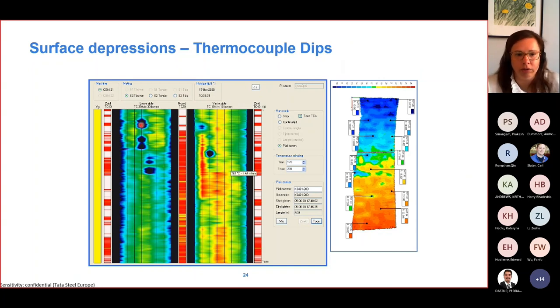And this is also associated with thermal stresses, because here it has another temperature than there, very local, between this area and the other area which is attached to or touching the mold. Because it detached, it cannot solidify properly. What we get, if you take out a steel shell and scan its thickness, is that the thickness is not even. That's really not good news, because it could have a lot of thermal stresses, but also a lot of imperfections, and it could even lead to cracking. So a test on a lab scale gives us so much information directly related to a process parameter and a process defect, which is very, very valuable information for us as industrial partners.